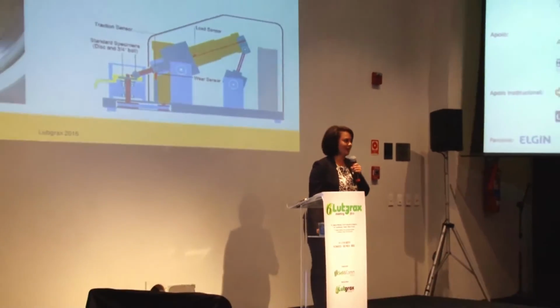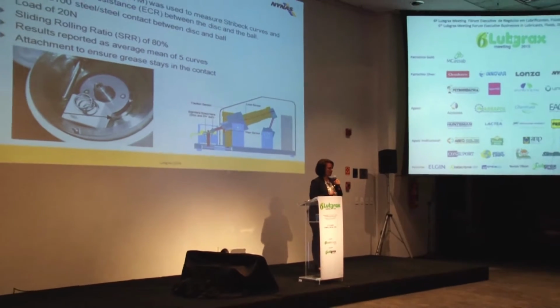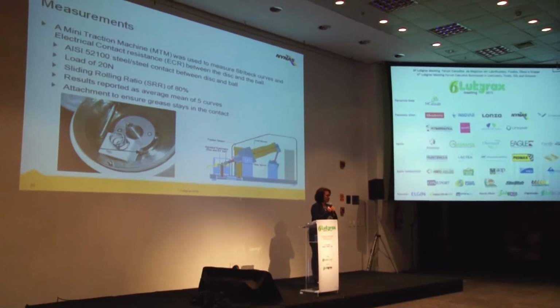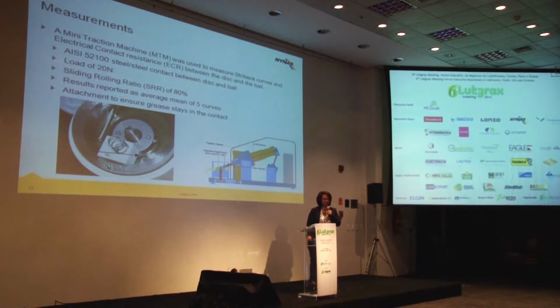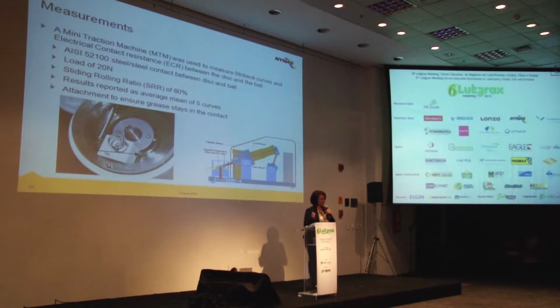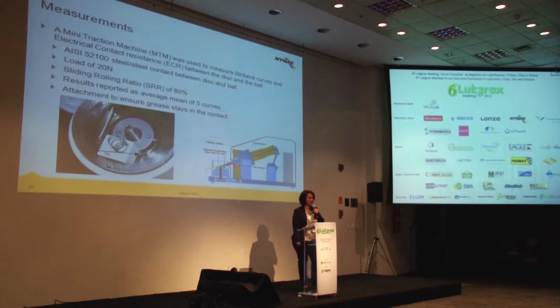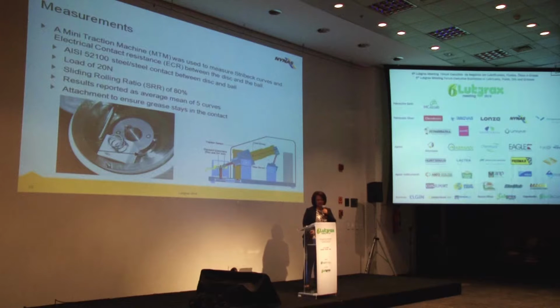So now looking at the high temperature analysis. I decided to investigate the frictional behavior at high temperature, being 110 degrees, because this was a lithium-based grease, so these are typical multi-purpose greases. We usually have recommendations of a maximum application temperature of 110 to 120 degrees C. So a mini traction machine was used to develop Stribeck curves. And I also had some ECR results, or electrical contact resistance results. I'll explain a bit further.